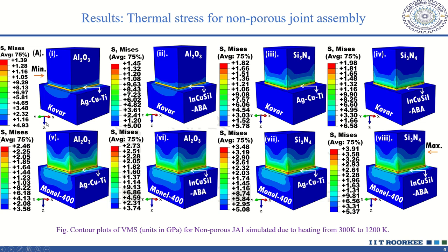It is found that this C1 combination, which corresponds to alumina ceramic, Kovar metal alloy and Ag-Cu-Ti brazed alloy, possesses the minimum von Mises stress, that is 1.39 GPa, and others are having the higher value. So this one combination is the optimal material combination out of these 8 ceramic metal composite material combinations.